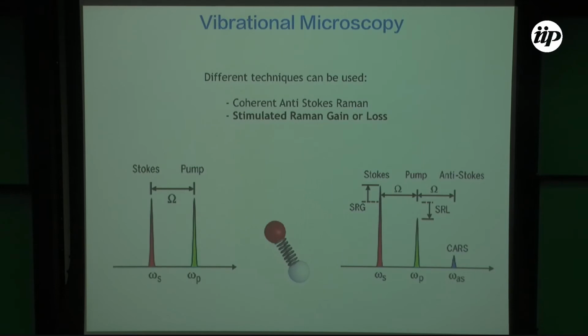So there are different techniques that can be used in order to see this effect. One of them is coherent anti-Stokes Raman, okay, that I have already shown some results on graphene and boron nitride. So basically in coherent anti-Stokes Raman, I have two pump lasers, omega S and omega P, such that the energy difference between them matches the frequency of some vibrational normal mode in your sample, okay? And then you're going to observe an emission of the CARS signal, which is the four-wave mixing signal that is in resonance with the phonon state, okay? And then you can detect this light, and you're going to measure this CARS process.